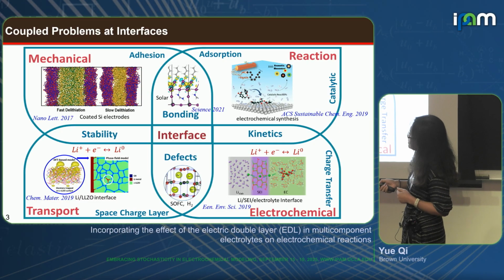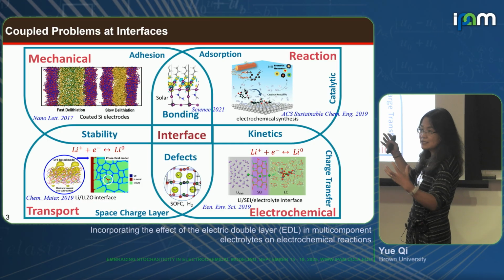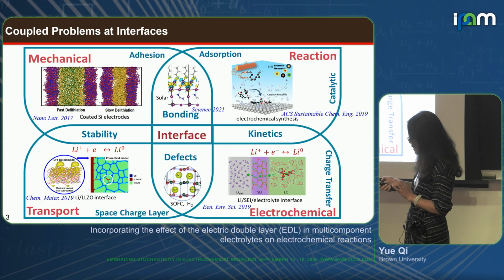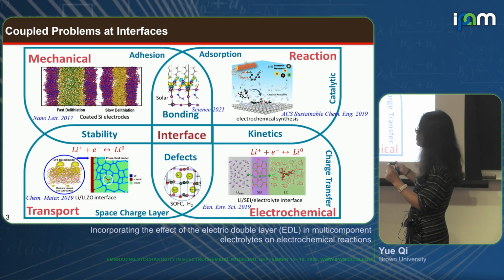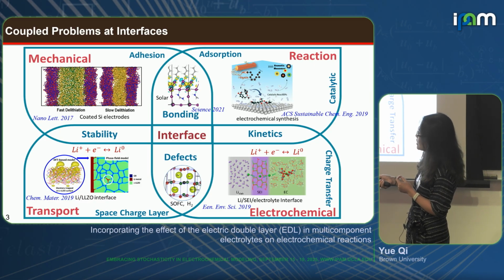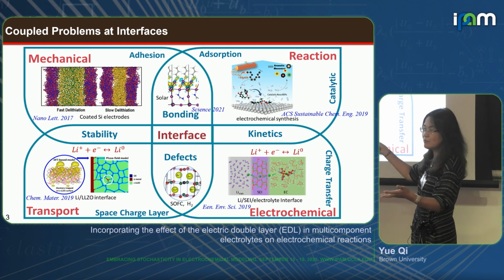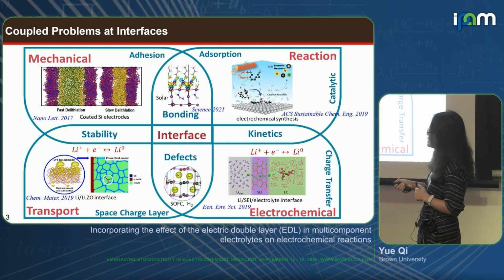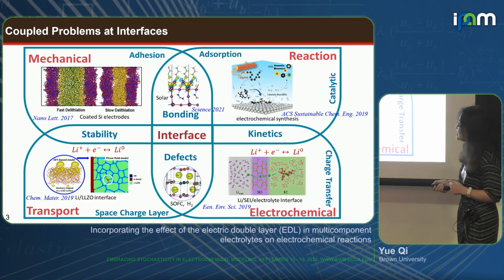Or this is a solid electrolyte work. So this is polycrystalline, like synthetic powders, like lithium lanthanum zirconium oxide, which is one of the solids that has very fast ionic conductivity. But because they are sintered particles, you have defects. You have grain boundaries, pores, and pore surfaces, and those pore surfaces can trap some electrons. The electrons may not stay in the liquid long, but they could stay in the solid long, and then they can reduce the lithium. So you have some lithium metal inside of the electrolyte, and then when they connect, it shorts the circuit. Right? So that's an example of lithium and the electron not meeting at the right place.